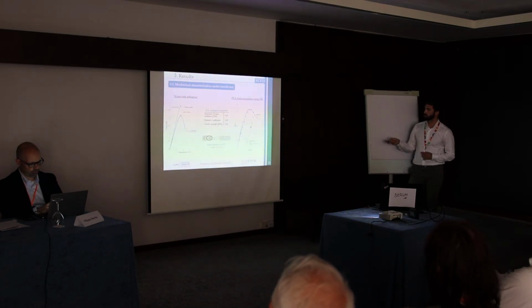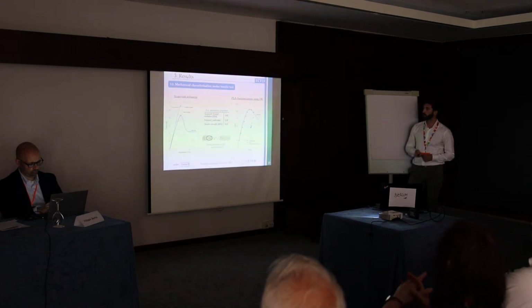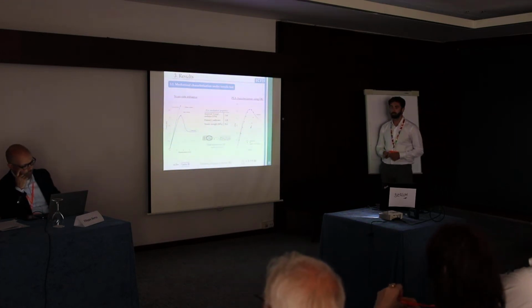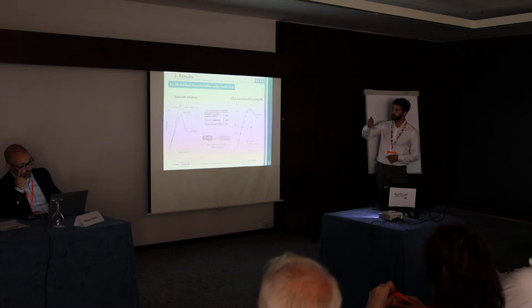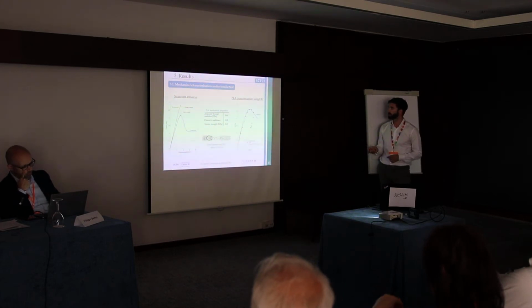Okay, you can see the elastic recovery of the material here in our region of interest, and in the middle the table with the main PLA mechanical properties, like the apparent Young's modulus, the Poisson coefficient, and the tensile strength that we use in the model, in the numerical model.